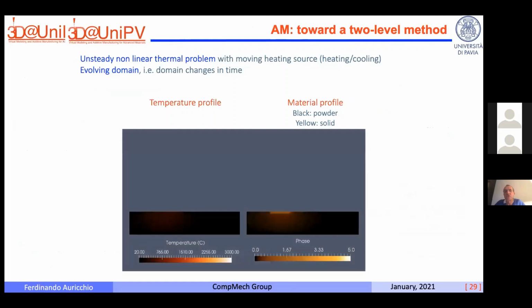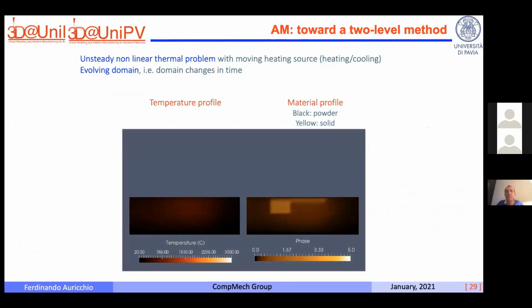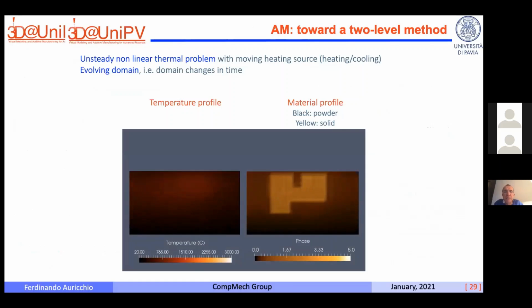And clearly you can try to do everything also not on a fixed domain, but on a domain that's evolving. And here on the left, you can see some preliminary results which show the temperature profile, which increases progressively because the laser is turned on and off. And on the right, you can see that the component is progressively building up. Okay.